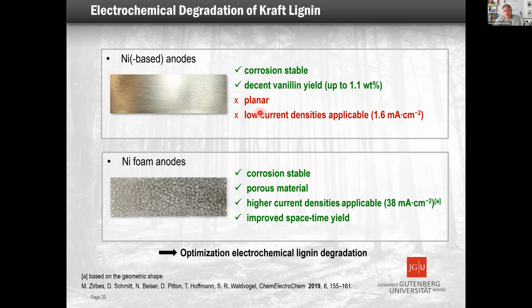The problem with the planar ones is that you have a certain surface area which you cannot enhance, and the current density has to be relatively low. A good solution is to go to nickel foams because you get them very easily for different applications. They are also corrosion stable and porous. You can go for a much higher geometric current density, and this gives an improved space-time yield. Therefore, the optimization for the lignin degradation seems to be given.